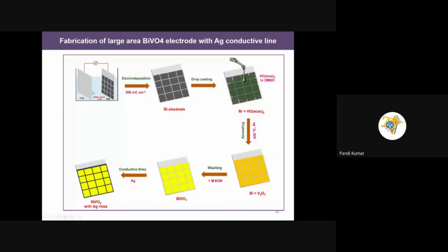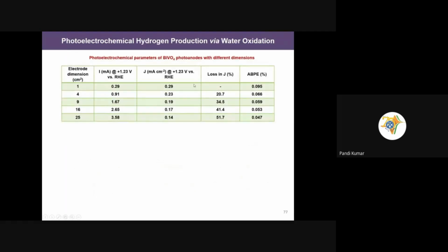Then we wanted to see how we could fix it. Somewhere I was on Facebook, and while scrolling I saw this picture. Then I got the idea, and accordingly I modified my electrode. Rather than the plain electrode, we made a grid pattern, and we came out with this kind of electrode. When I used the plain electrode, at 4 centimeter square there was a 20% loss. When I reached 25 centimeter square, almost 50% loss in the efficiency as well as the hydrogen production rate.